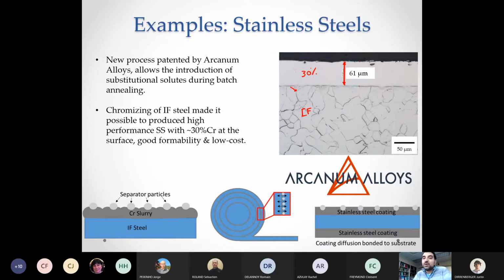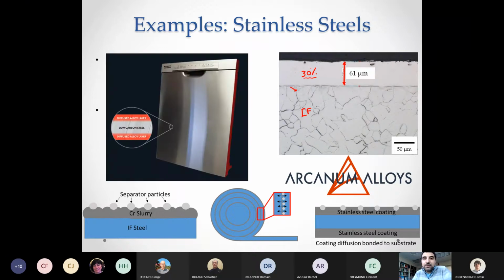That deposits chromium on the surface, and by controlling the process, the temperature and the time, they can control the diffusion of chromium into the steel, and they can control the thickness and the concentration of this surface layer. So it can be optimized for different applications. So this might be a very promising technology in the future, for example, to build appliances. In the case of appliances, the nice stainless steel finish on the outside is mainly for appearance. It doesn't do anything else, right?